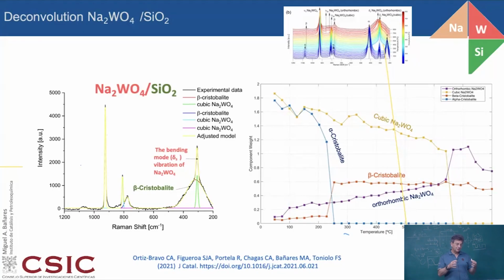And then you have to corral the reality to say, okay, how can I get to see that? I make operando synchrotron, but I see very nicely vanadium, I cannot see much of cerium. I make nanoparticles and then I can see cerium nicely. I make computational chemistry to understand what is happening there. I do complementary studies. Even the group of Sauer, they were also doing atomic force microscopy and scanning tunneling microscopy to assess the interaction between vanadium and cerium. So then you end up doing a lot of complementary studies to describe what is happening there.